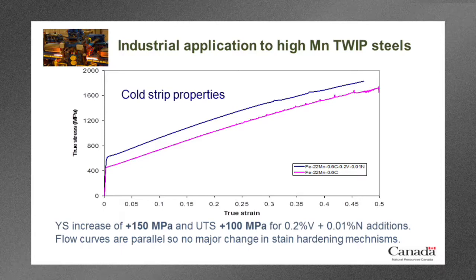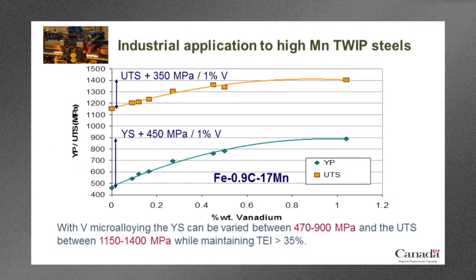We don't see a big decrease in ductility. So it's a very interesting effect that the vanadium has had there. And here is similar data, but this time as a function of the amount of vanadium that we add. You can see the ultimate tensile strength as we go from 0 vanadium up to, in this case, 1%. The ultimate tensile strength was improved by over 350 megapascals at 1% vanadium, and the yield strength could be increased by 450 megapascals. So it's a very, very strong strengthening effect. In all cases, the total elongation was above 35%.